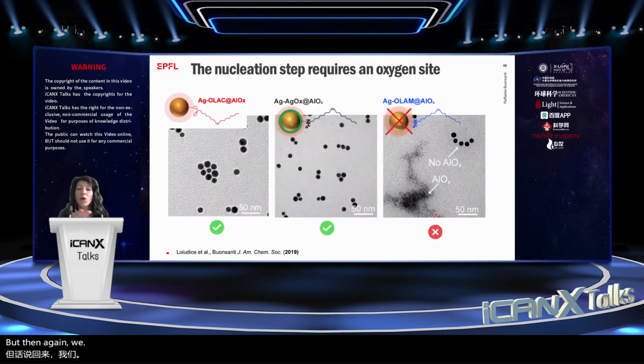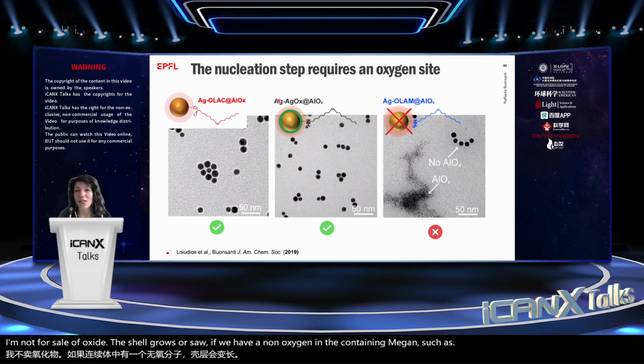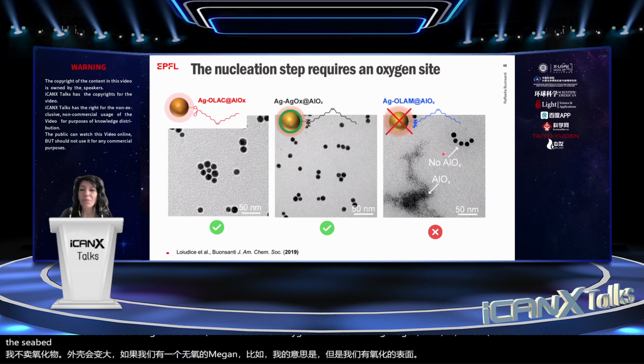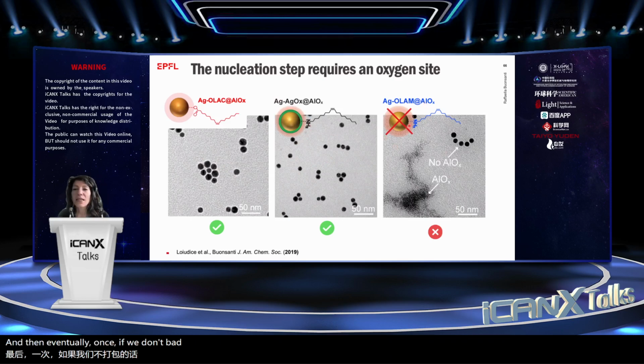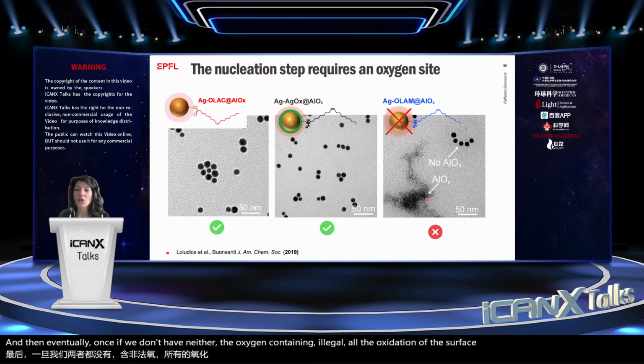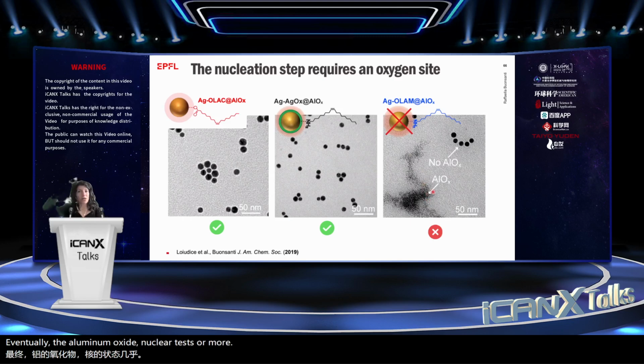But then again, we were interested in the chemistry by which these materials nucleate, by which the shell nucleates and grows. And what we found is that if we have silver nanoparticles, for example, with oleic acid, the shell can grow. You don't see it here because it's a thin amorphous shell of oxide. The shell grows also if we have non-oxygen-containing ligands, such as amine, but we have surface oxidation of the silver. And then eventually, if we have neither oxygen-containing ligands nor oxidation of the surface, the aluminum oxide nucleates homogeneously but does not form shells around the nanocrystals. So we learned that an oxygen site is needed.